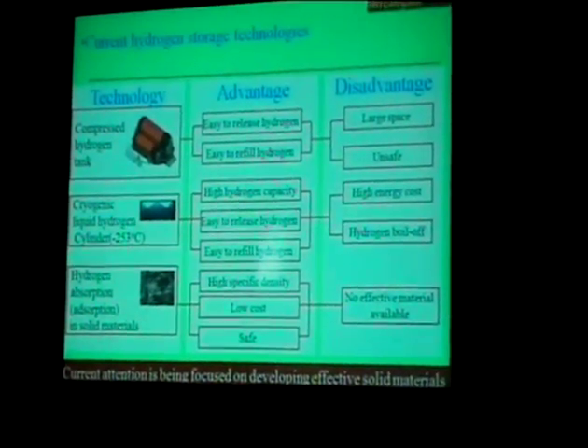The second one, we can use liquid hydrogen. We liquefy the hydrogen into the cylinder. That way, we can easily get a high capacity and easily release and refill the hydrogen. But when the gas transfers to liquid, you spend a big amount of energy. Actually, 20% of the hydrogen energy is used to liquefy, so you lose 20% of the hydrogen energy.